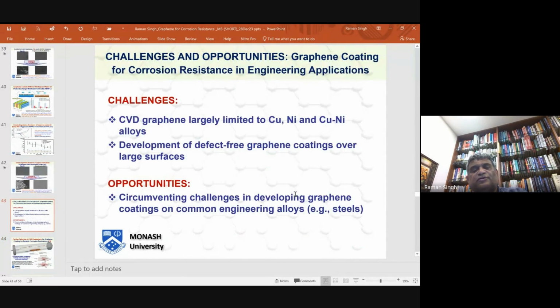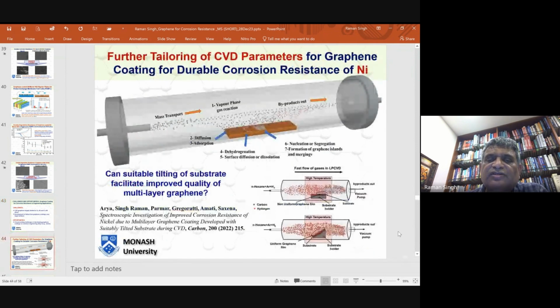So what I showed you so far is that we could develop graphene on copper and copper nickel alloy, and they showed very good corrosion resistance, but we worked on very small samples. Can we develop this quality graphene on large area? And more importantly, can we develop graphene on alloys which are of common use, like mild steel? And as I alluded to earlier, that it is challenging. So we started to work on improving our parameters.